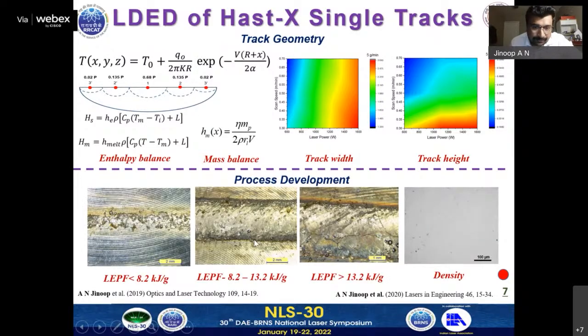This is the most critical aspect because we have three different zones for processing the material. Every material has a different zone of processing where we can get good quality deposition. So this is one zone where we could get discontinuous deposition, and this is a zone where we could get continuous deposition, and the zone where we could get crack deposition.